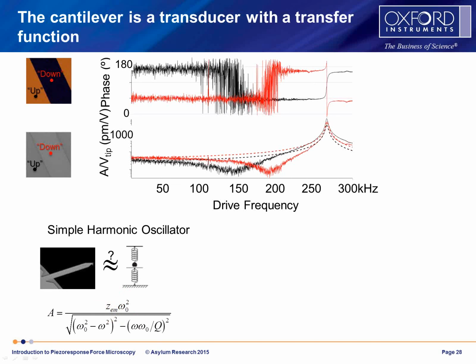The thing is, these dashed lines here, the red and the black curves, are the simple harmonic oscillator fit to these curves. And you can see while the curve fits okay near the resonant frequency and near the base, there's this whole intermediate range where it very much does not fit. So what that tells us, at least for this particular set of data, is that the simple harmonic oscillator model just isn't quite correct. It doesn't capture all the dynamics of the system. So we need a different model.